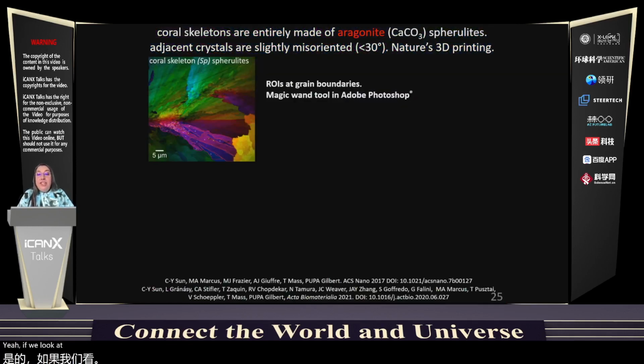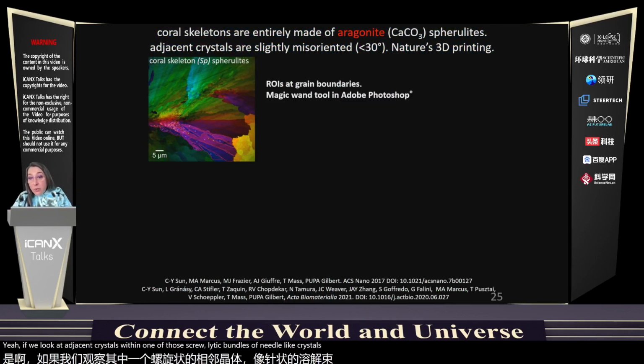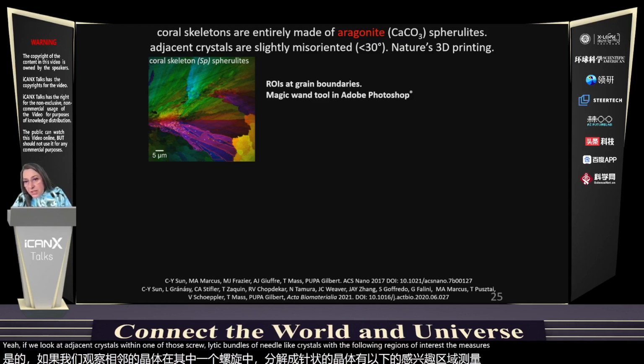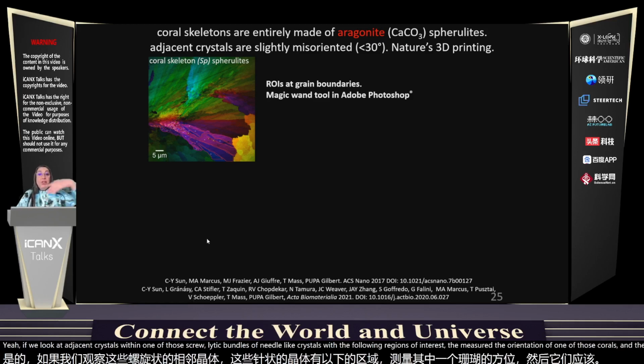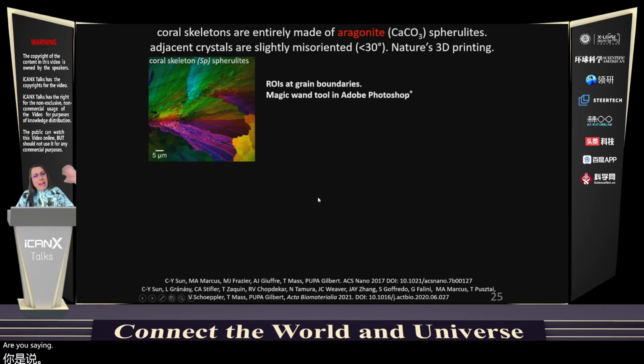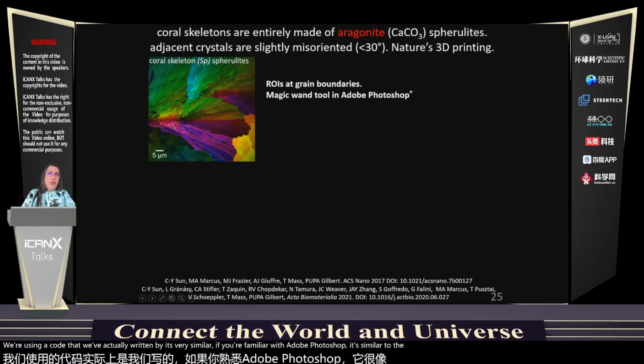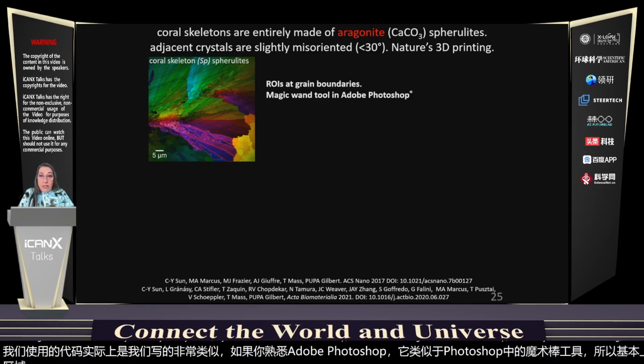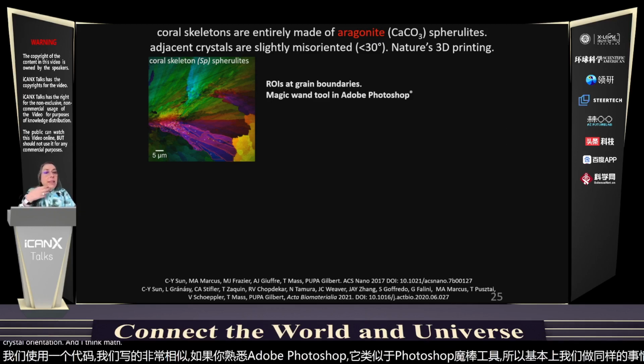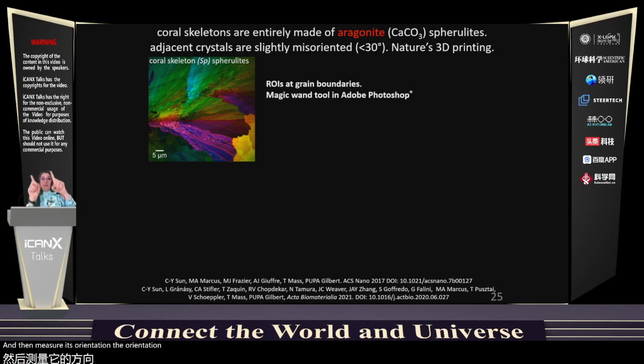So, if we look at adjacent crystals within one of those spherulitic bundles of needle-like crystals, we define regions of interest, measure the orientation of one of those crystals, and then measure the orientation of the adjacent one using a code that we've actually written, but it's very similar to, if you're familiar with Adobe Photoshop, the Magic Wand tool. So basically, we select one region that's defined by a color that quantitatively means crystal orientation in a PIC map, and then measure its orientation, the orientation of its c-axis in three-dimensional space. So we do the dot product of those two unit vectors in three-dimensional space and find the angular distance.